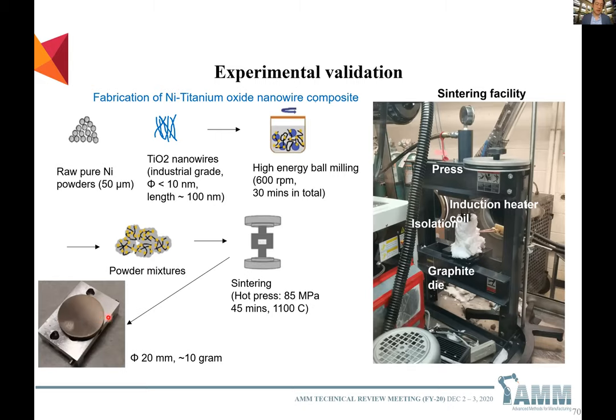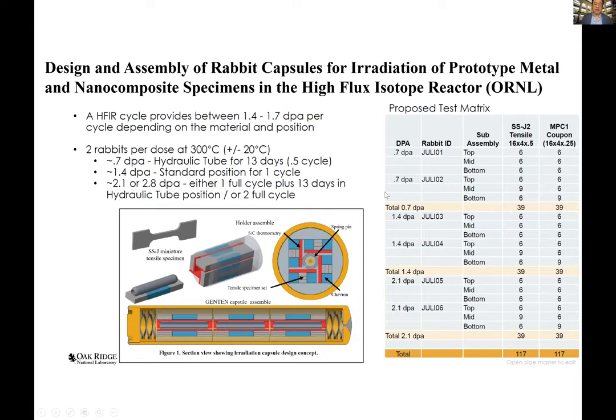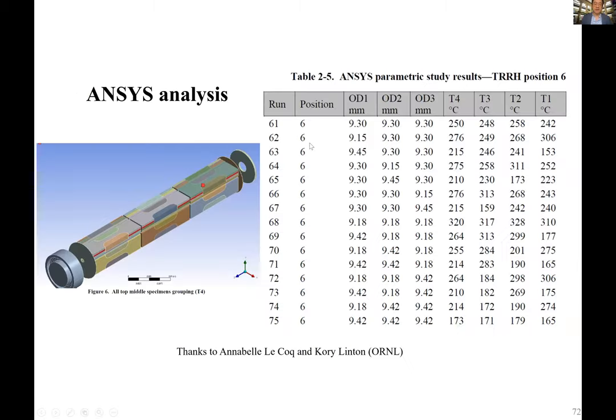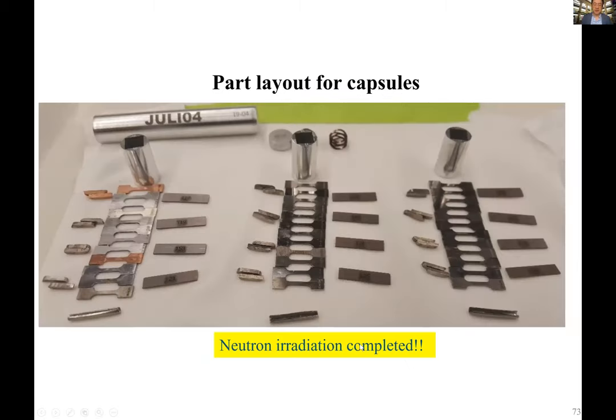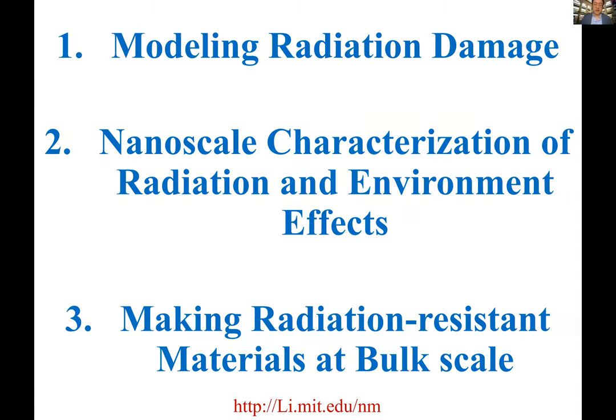We have made samples like this, and we have recently put them into the HFIR reactor at Oak Ridge. And we have developed all these samples. Actually, we just have received these samples fully irradiated to a few dpa. So we're now analyzing different 1D nano dispersion nanocomposite behavior post neutron radiation. So with that, I'd like to finish.